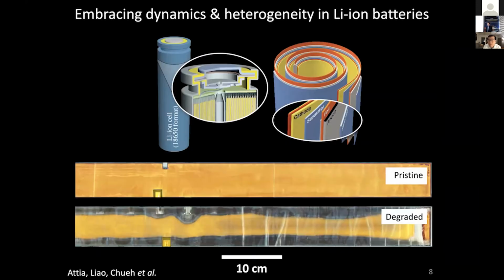Let me give you a few examples from Stanford that look at the heterogeneities and dynamics at all length scales. So this is a study of just taking a battery apart in the charged state. So the color you see here is due to the color of graphite. When graphite has lithium inside, it's gold in color. And when it doesn't have lithium, then it's black. You can see the top is a pristine battery that's lithiated uniformly. On the bottom, you have a degraded battery where it doesn't lithiate near the edges.